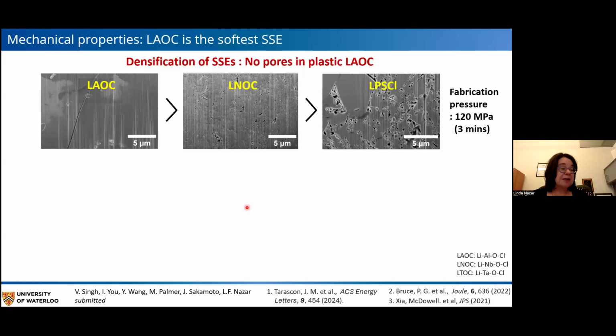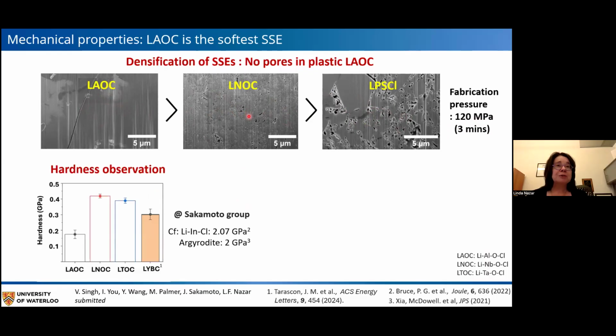So I'll just end off in the last 5 minutes talking about some mechanical properties. This shows the lithium aluminum oxychloride, the lithium niobium oxychloride, and argyrodite all pressed at 120 megapascals for 3 minutes. And you can see that there's pores in the argyrodite. We normally would press at a much higher pressure, but we did this in particular so we could compare the three. And you can see in this situation, the LAOC is completely dense, and the LNOC, the niobium oxychloride, has a little bit of pore structure.